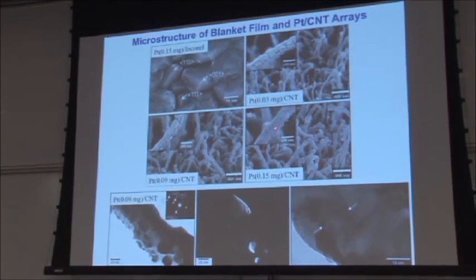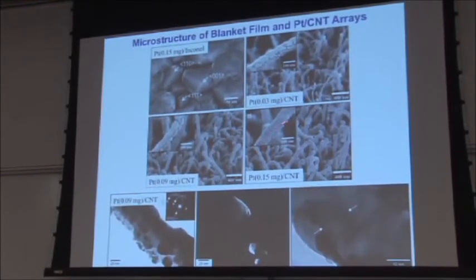And when we deposited the same mass loading of platinum on the carbon nanotubes, as expected, even at high temperatures, the platinum really did not wet the carbon nanotubes well. So basically, here's the low mass loading, higher mass loading, and 0.15 milligrams of platinum on the carbon nanotubes. And especially, this is a spotted deposit, especially on the back side, you see a lot of isolated platinum crystallites. There's quite a bit of de-wetting. The sputter flux is coming in this way.